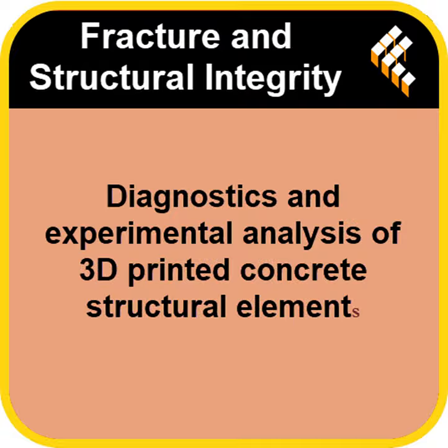But, and this is a big but, the variability was still very high, a coefficient of variation around 25%. That level of inconsistency is still a major risk, even if the average strength is good. Okay, so destructive testing proves the risk, but obviously you can't just smash every column on a construction site to see if it's good. Of course not. So how do you check the quality beforehand?